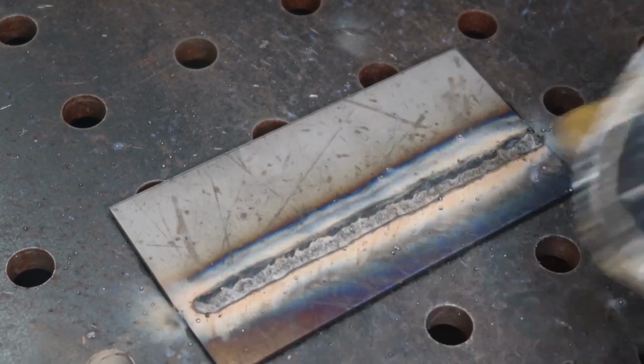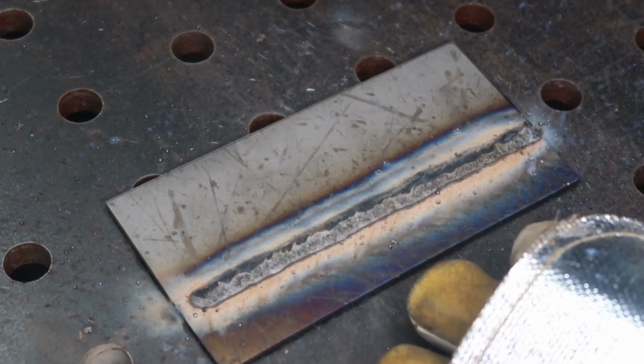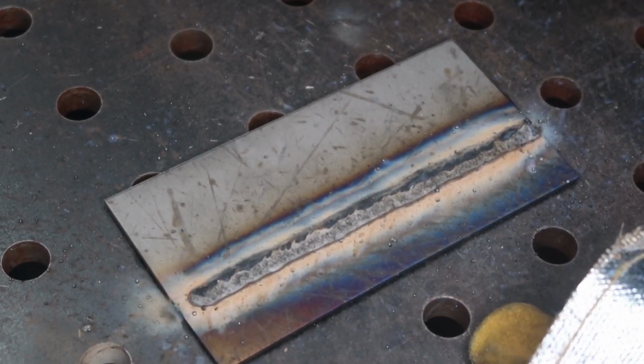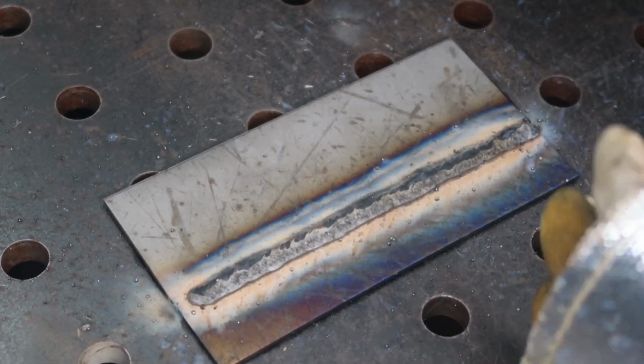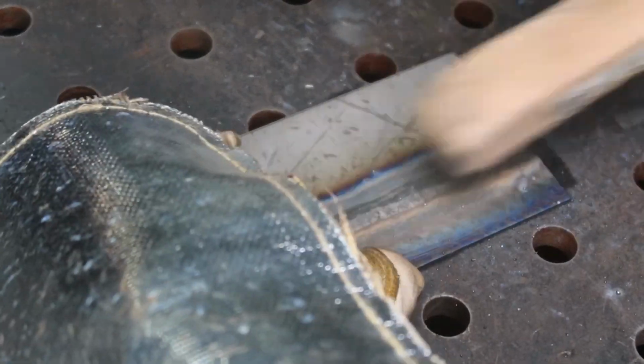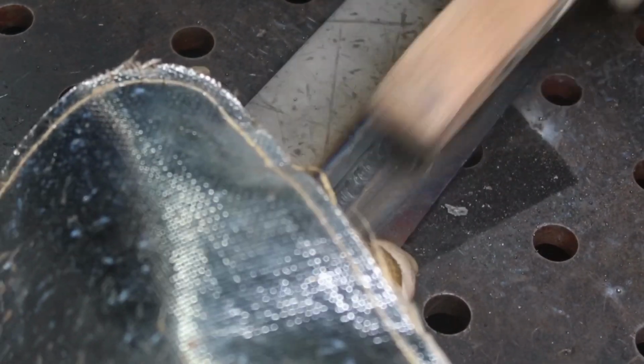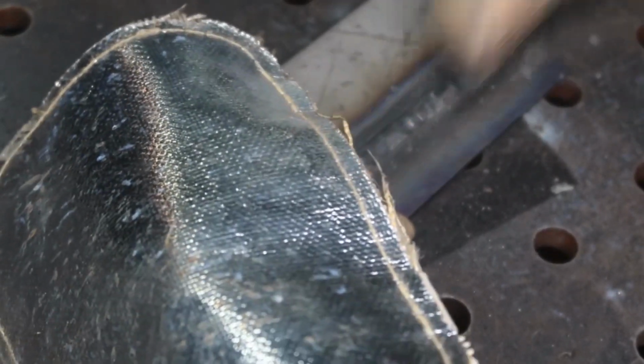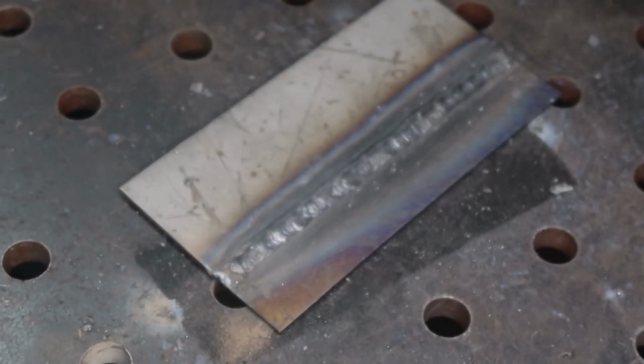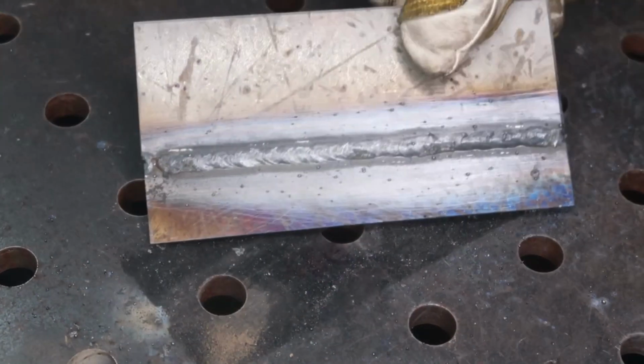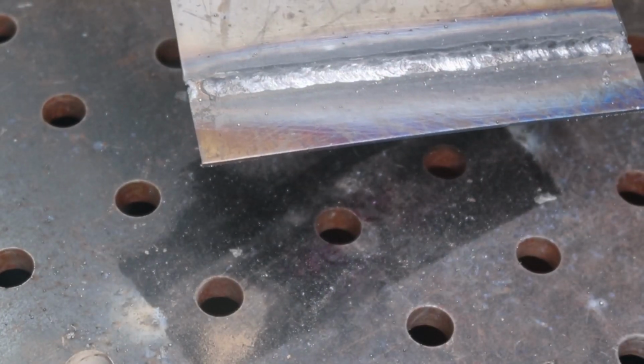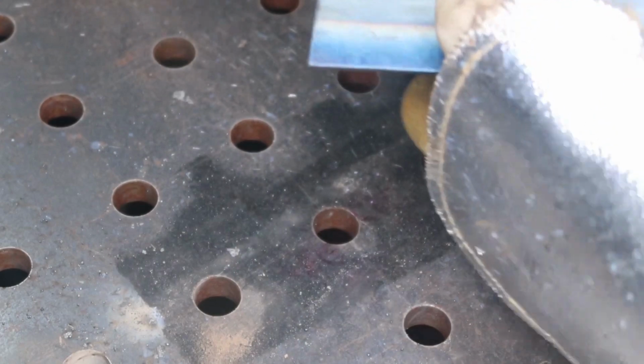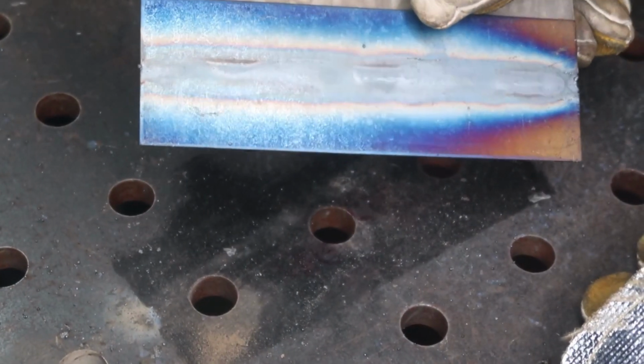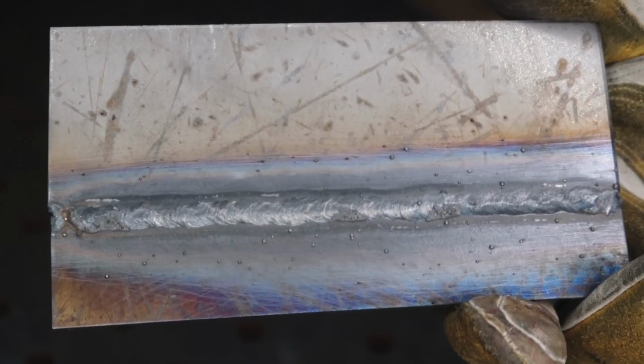We ran our first pass here on this 80,000 lap joint with the self-shielded flux core. We're just gonna clean it up real quick, see what we got. So here we got it cleaned up on 80,000. It actually ran pretty good. So we'll take a look at the backside, see what we did. That's a real nice weld.